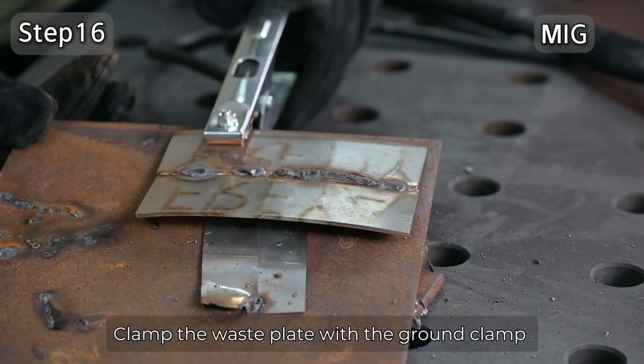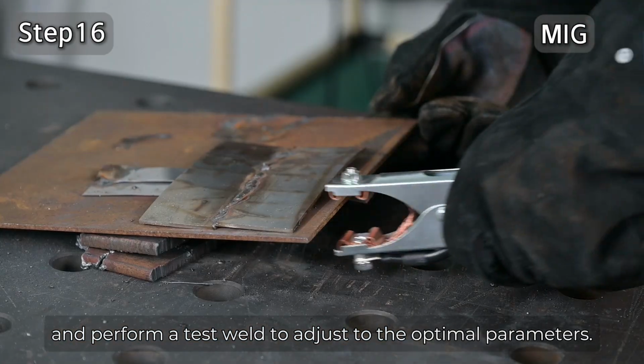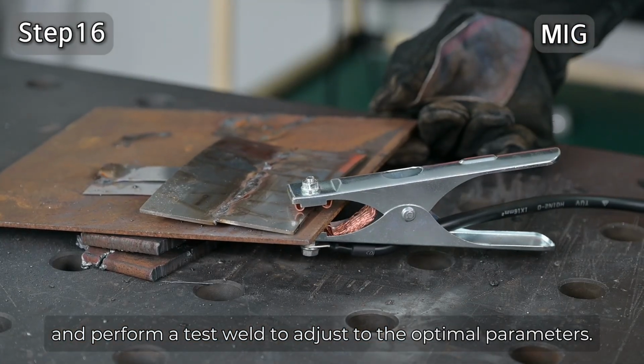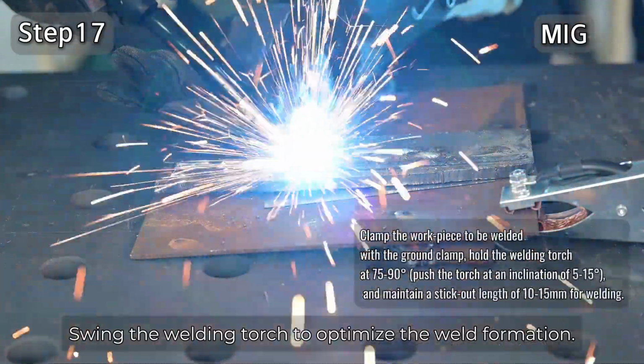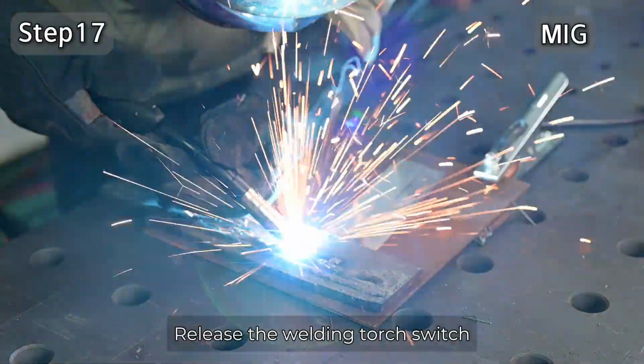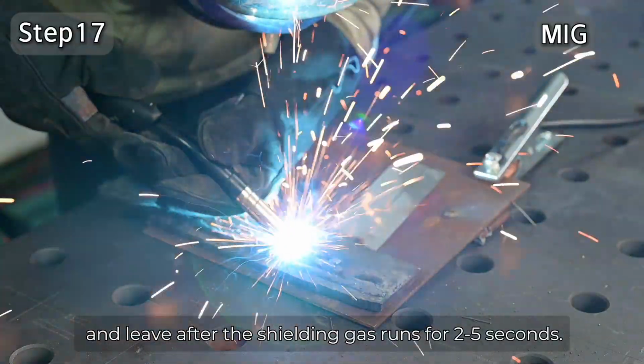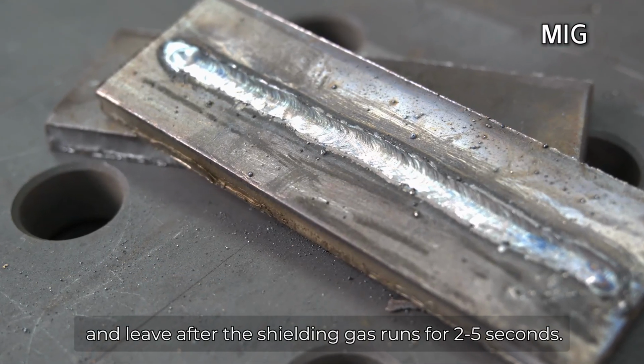Clamp the waste plate with the ground clamp and perform a test weld to adjust to the optimal parameters. Swing the welding torch to optimize the weld formation. Release the welding torch switch and leave after the shielding gas runs for 2 to 5 seconds.